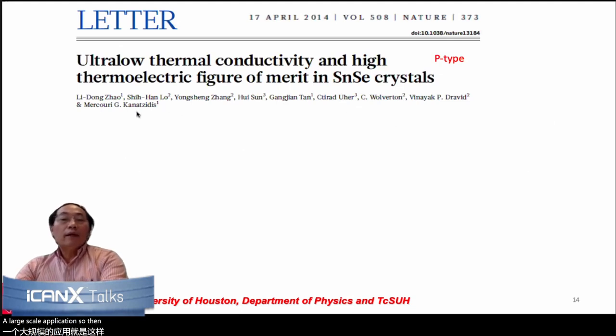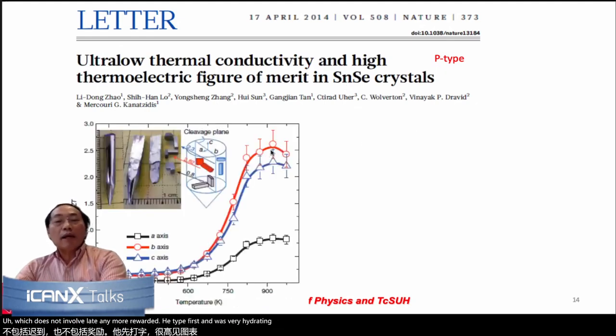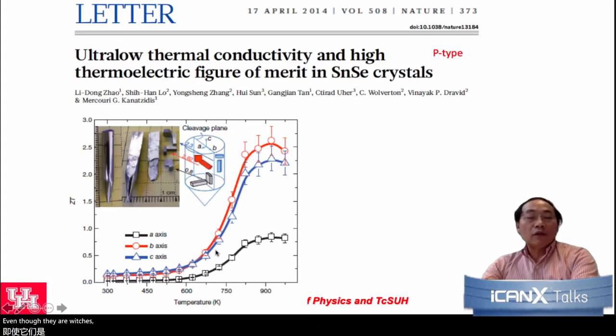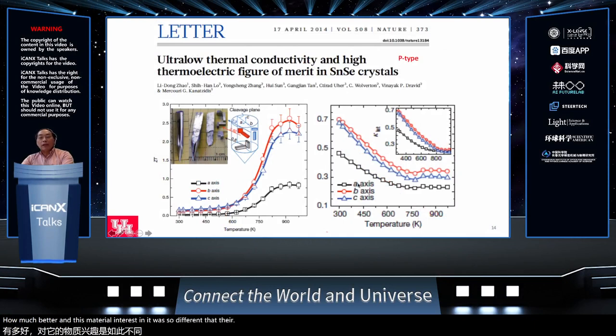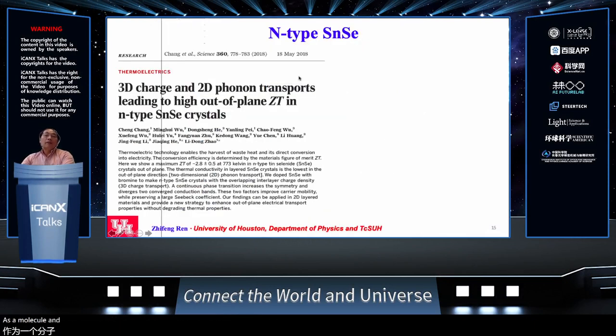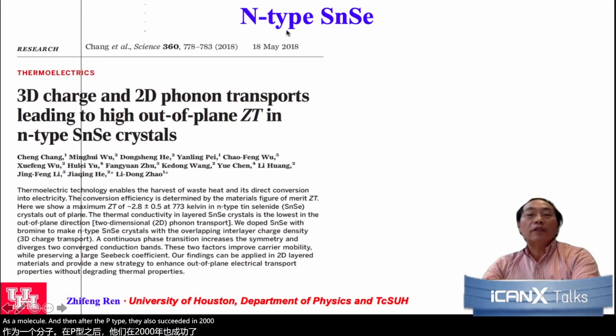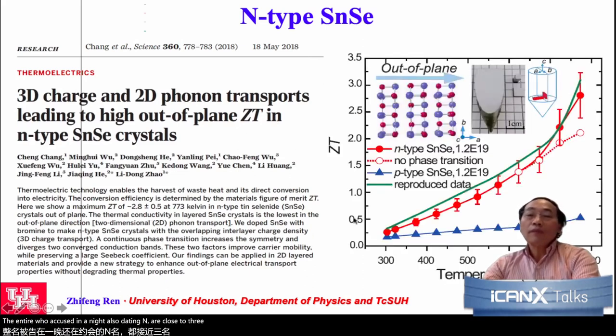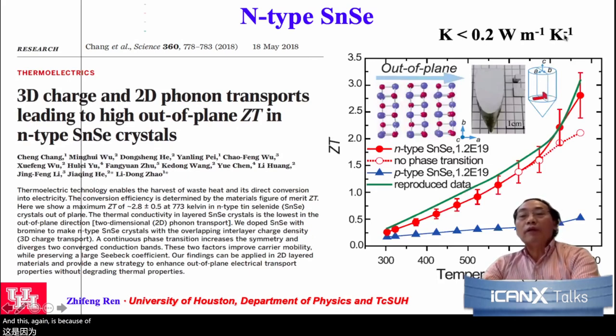So then Lidong Zhao, now in China, came up with this new material, tin selenide, which does not involve lead anymore. He reported P-type first, with very high ZT above 2.5, even though the ZT at lower temperature is not good, but later on different ways were reported to improve the ZT, so maybe the average ZT is much better. And this material, interestingly, in different directions also has very low thermal conductivity. And after the P-type, they also succeeded in 2018 with N-type tin selenide, with ZT close to 3 even. And this is, again, because of the very low thermal conductivity.